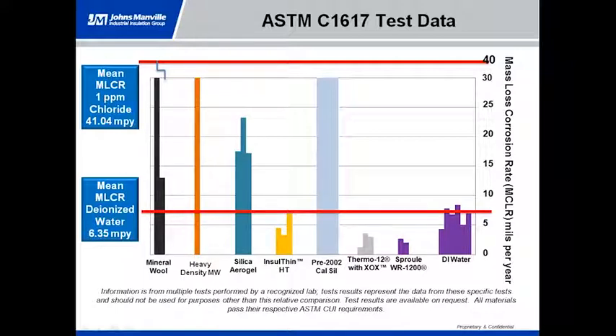The 1 part per million chloride solution is more like 41 mils per year. Now, when we look at all these materials, they pass their respective ASTM rates, but as you can see on here, there are very different corrosion rates. Now, one of the takeaways here is that the pass rates are established by whether you're using deionized water or the 1 part per million chloride solution. So in this case, using the DI water